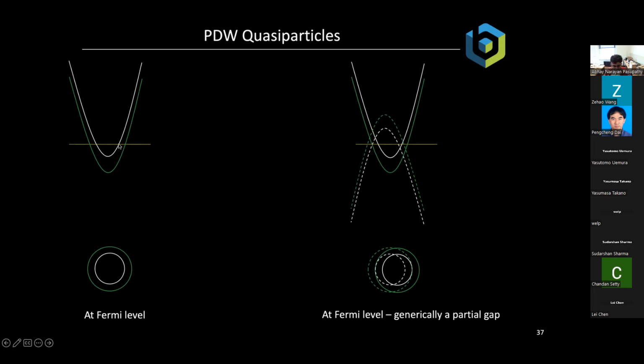The pairs are formed between K and minus K plus Q. So I have to construct the particle-hole symmetric band structure, and I have to shift them by this momentum Q, which is where the pairing happens. And so here there will be a gap that opens up, and here there will be a gap that opens up. But in general, there will be regions of the Fermi surface.